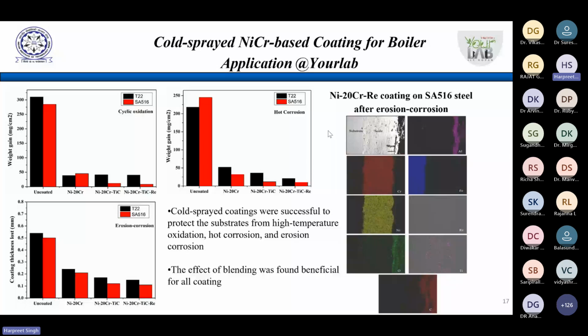Another thing which happens is, when this fuel burns, you will have some fly ash particles which are going up, right? And these fly ash particles have some harder phases also, which will impinge on the boiler tubes, and they will also erode the boiler tubes. So you get erosion also. So this combined thing, hot corrosion or high temperature corrosion, usually accompanied by erosion, causes a lot of damage to the boiler tubes. So the remedy here is that we usually apply some coatings on these boiler tubes, right? So we have some cheaper material as the substrate of the boiler tubes, and on that we add some highly corrosion and erosion resistant material. So this study is basically about that.